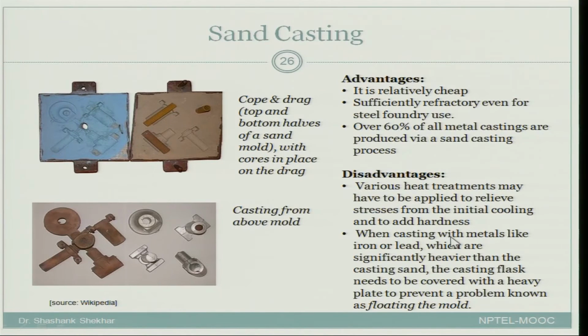Another disadvantage is when we are doing casting with metals like iron or lead, which are very heavy metals, then on top of the cope you need to put some heavy material or heavy weight. Why is that? Because the buoyancy of these metals may cause the cope, or the top part of the mold, to start floating, and this kind of problem is called floating mold. To get rid of this, you must put some heavy weight onto this sand casting.